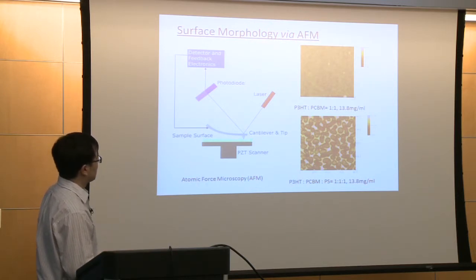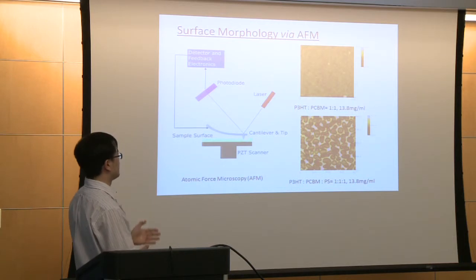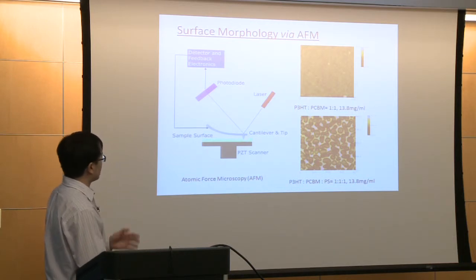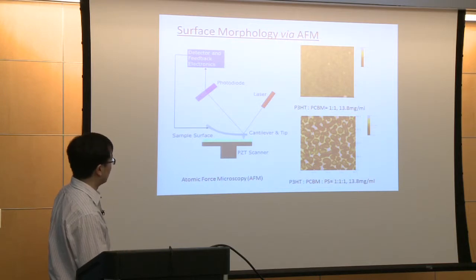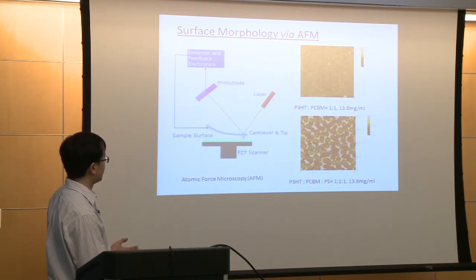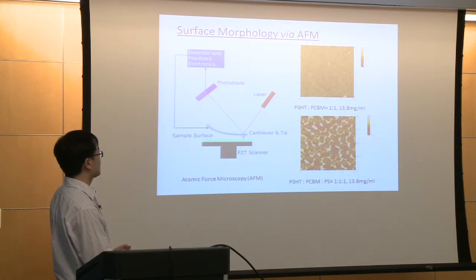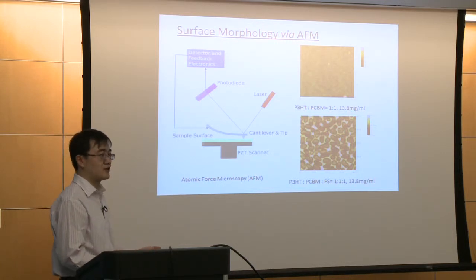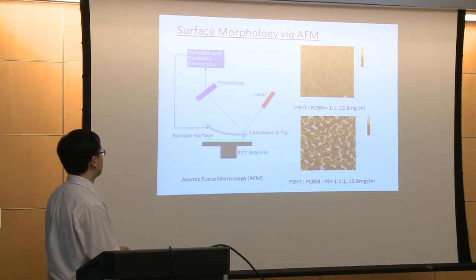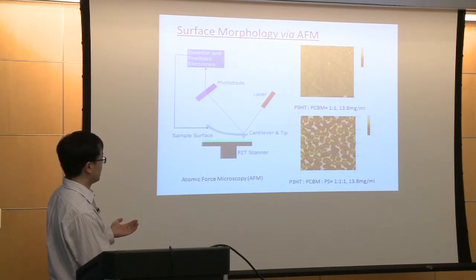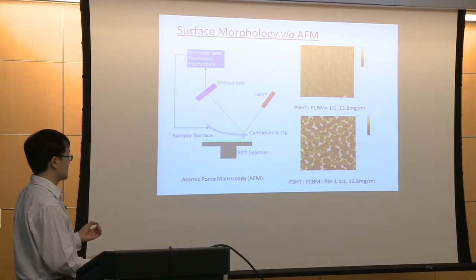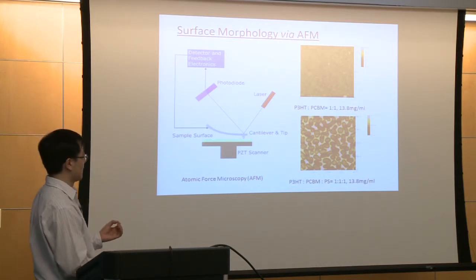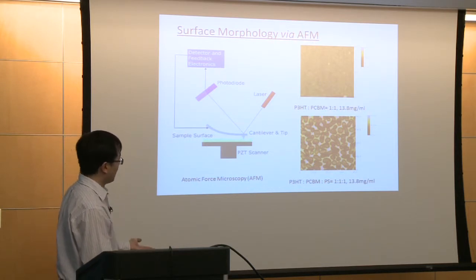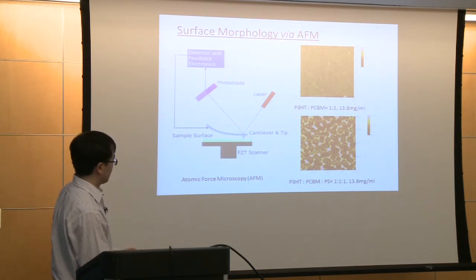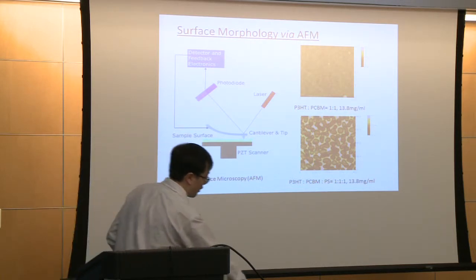Okay, so the images on the right-hand side are the images we get from the AFM. The top one is the morphology for the sample without polystyrene. It's just P3HT and PCBM, and you can hardly see anything on the surface, which means the surface is very smooth. And after we introduce the polystyrene into the system, you can see very significant phase separation on the surface, which means there are upper areas and lower areas, and they are in very good order on the surface.